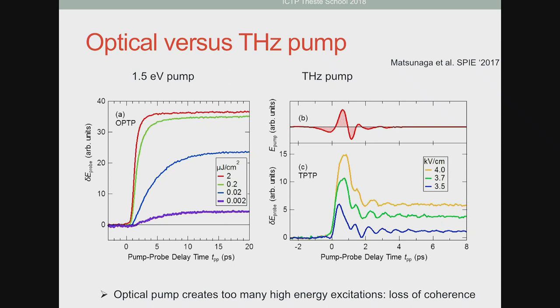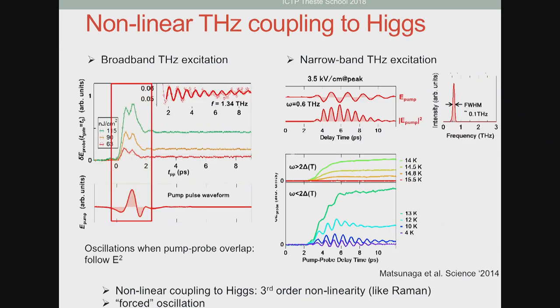And the reason is presumably relatively simple. When you shine 1.5 electron volt light, you are creating a bunch of electron-hole excitations of very high energy. When they cascade, they break completely your coherence. So there is no hope of finding these 2 delta oscillations. And for that, you really need to use a low frequency light. So there is a loss of coherence when you pump with too high energy.